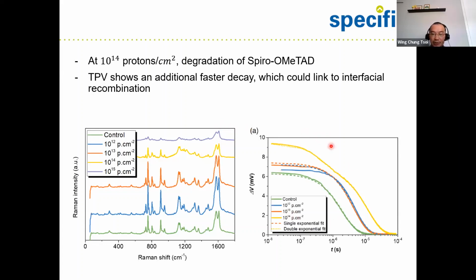And this is a study to show that at higher fluences, we need two exponential fits to fit the curve for this transient photovoltage measurement. Basically, we need an additional fit, which is a faster charge recombination. This could be attributed to interfacial recombination and could be consistent with the degradation of the spiro layer, which affects the interface between the perovskite and the spiro, the hole transporting layer.